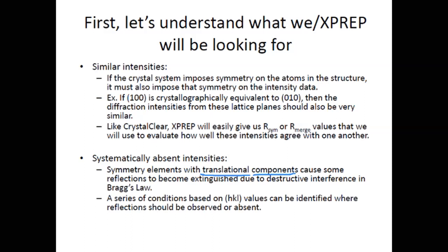Only those elements with translational parts can cause this destructive interference. So this does not include mirror planes, two-fold rotations, or inversion centers.